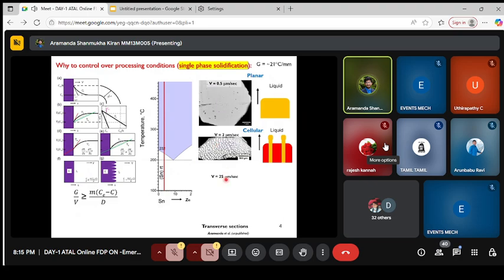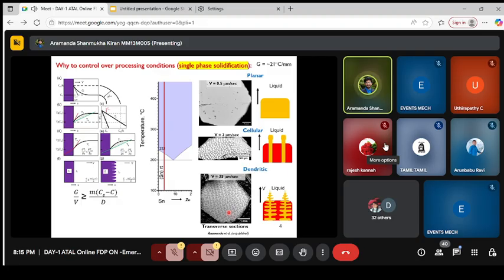And by increasing further, we can see something like a dendrite type structure with a completely periodic structure. So what it implies is the same alloy, same material, if you do a different process condition, the interior of the material is changed. That means by changing how you are cooling, you can change your material. That will change the property. That will change the entire material application. So that is where how you cool is more important, and how you get internal structure is very important. This is one example.